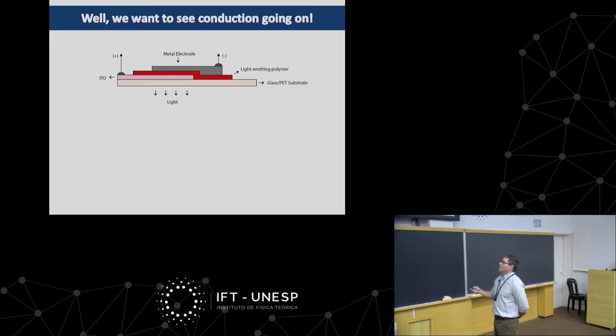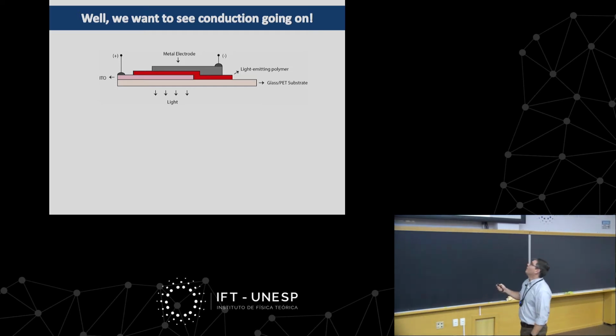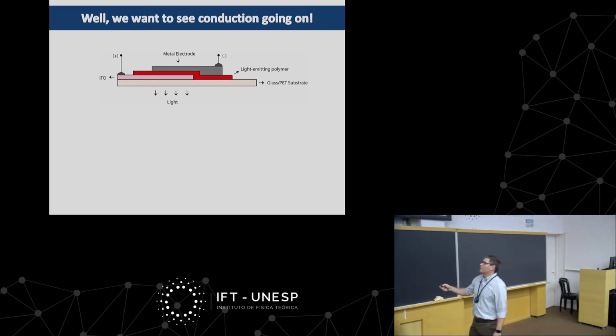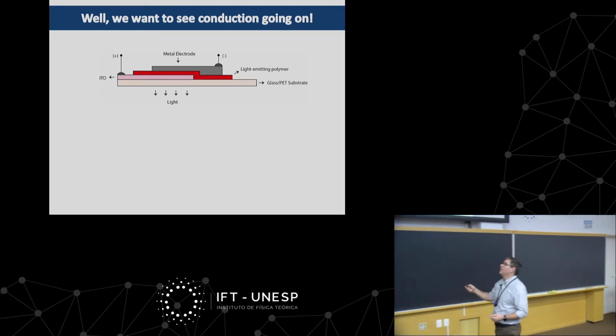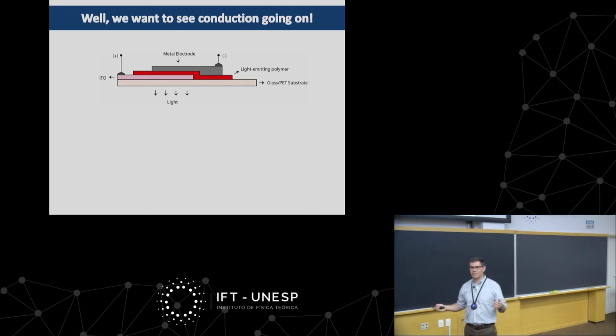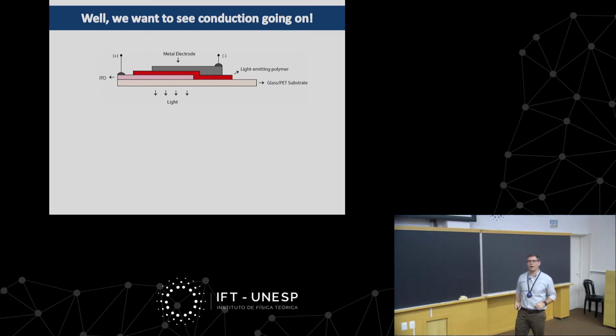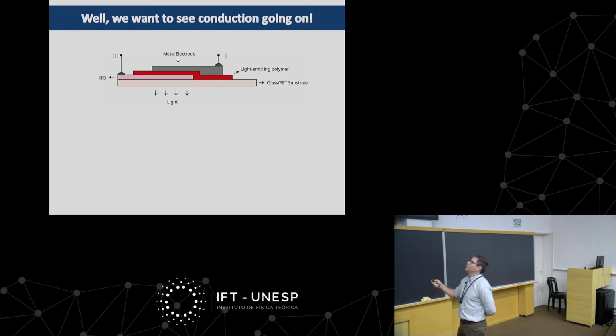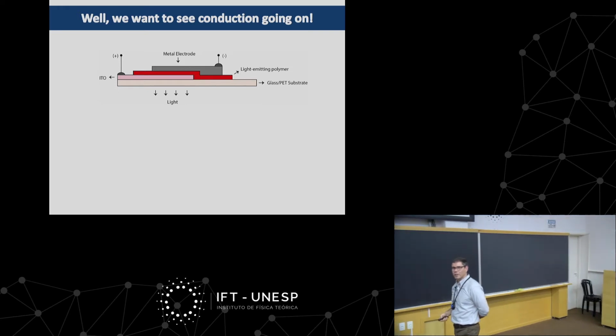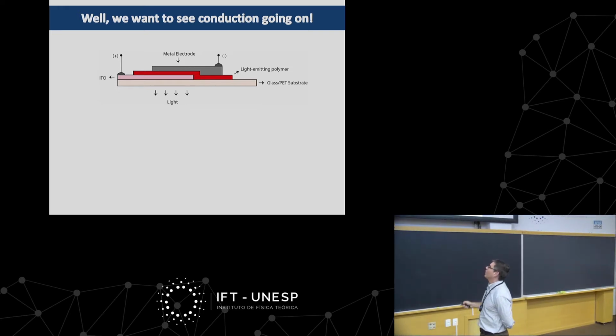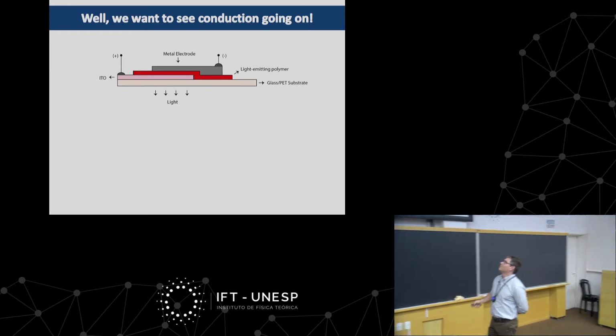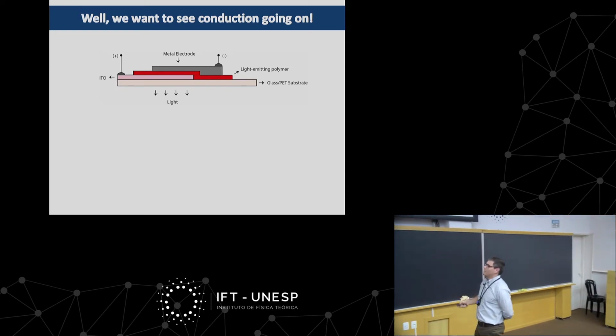And the way you do it is fairly simple. So you use a substrate. It could be glass. It could be a PET substrate if you want to make it flexible. Then you put a coat of semi-transparent electrode. This is the ITO, indium tin oxide. It's just an oxide. It's transparent. It's highly conductive. And you need that because you have to apply a potential across the film. And then you put your light-emitting polymer, one of those conjugated polymers. You deposit it on top of this structure, and you finalize the device structure by evaporating a metal electrode.